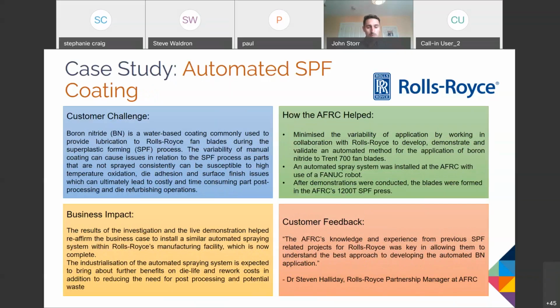So another example again with Rolls-Royce. This was one of the examples of a complementary process. So I mentioned a bit about coatings and lubricants that are used for the SPF process. Specifically, the lubricant boron nitride tends to be sprayed as an applicator to a component prior to the manufacturing process. And this allows it to be both an oxygen inhibitor and also prevent sticking to the die during the process. So it allows a bit of lubrication to more easily remove components at the end of the process.